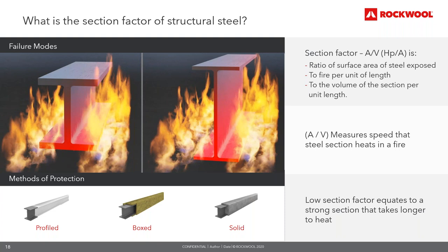So A is equal to the surface area of the steel exposed to the fire per unit of length, and V represents the volume of the section per unit length. Essentially, it's the measure of how quickly the steel section will heat in a fire, and therefore how much fire protection is required. A low section factor equates to a strong section, which when unprotected will take longer to heat to a set critical temperature than a relatively lighter weight section with a higher section factor. A steel section with a large surface area will heat up more than a section with a small surface area. In addition, the greater the volume of the section, the greater the heat sink, and therefore a smaller, thicker section will have a slower rate of temperature rise in a fire when compared to a large, thin one.